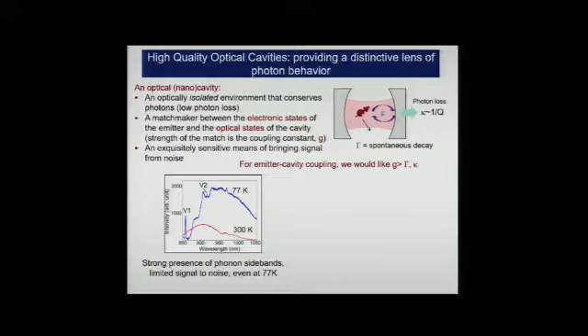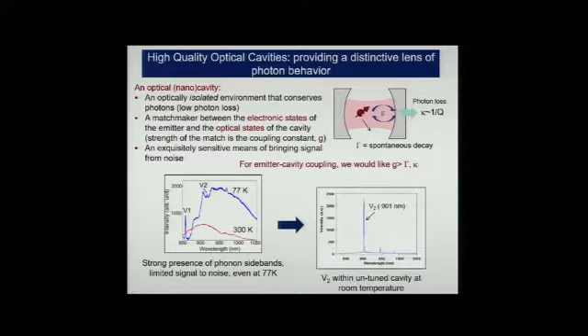So just to show you, as promised, that the cavity can do this, these are the spectra I showed you before. After we make the cavity, and I'll give you a little bit more detail of how we design the cavity, here is the cavity at room temperature, untuned. This is an untuned cavity. This is the emission signature of one of the transitions. The cavity has not been tuned. It's been designed to be close in resonance to one of the transitions, but it has not been precisely tuned. So you can see already the influence of the cavity. This is at room temperature.